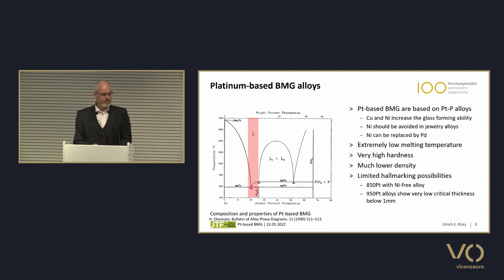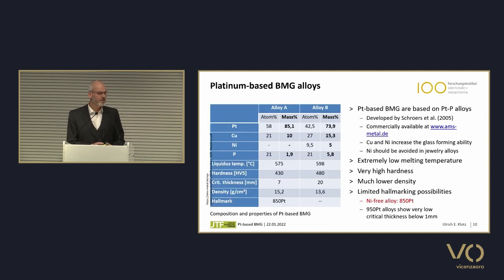So therefore, we were studying two alloys. I call it alloy A and B. Alloy A is the alloy with 85 mass percent of platinum. It contains copper and around 2% of phosphorus. And it has a liquidus temperature quite low, below 600 degrees, extremely high hardness, and it has a critical thickness of 7 millimeters. So this means this is the maximum thickness where you can cast the alloy under ideal cooling conditions. So 7 millimeters is a lot for most, or enough for most jewelry objects if they're made by casting.